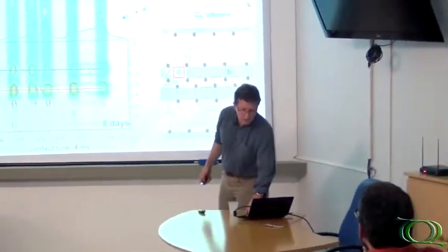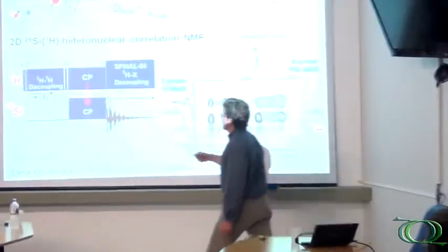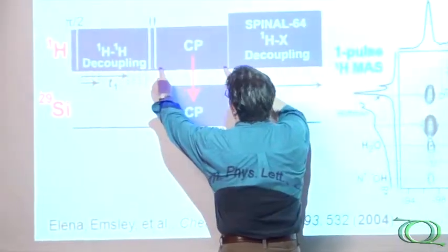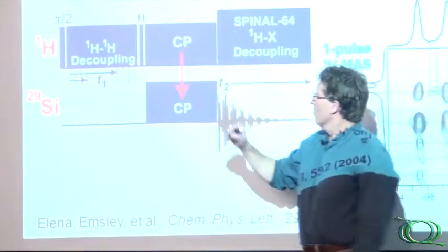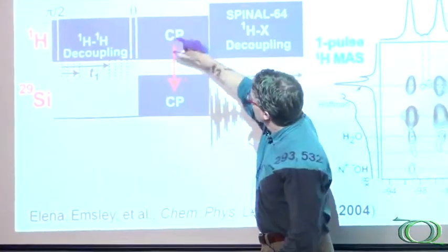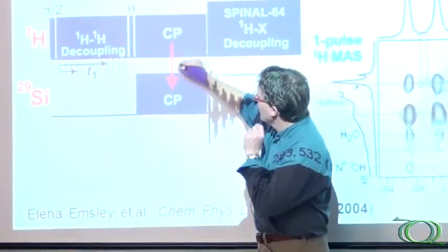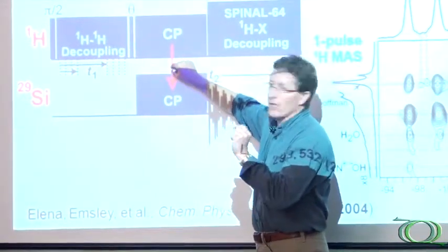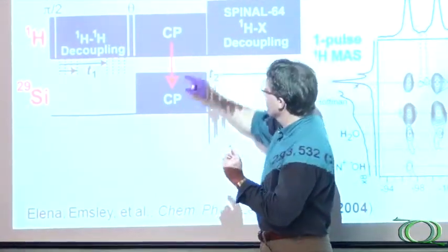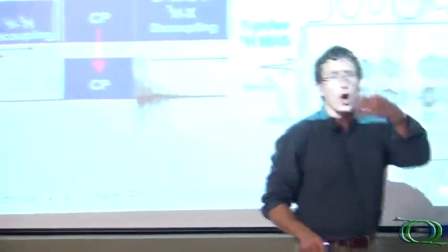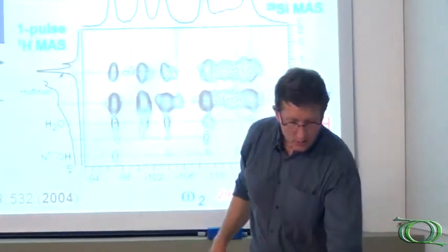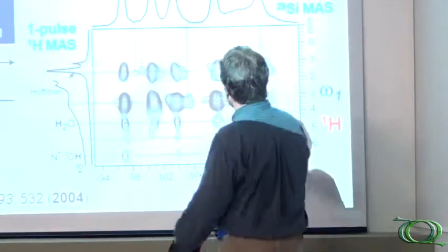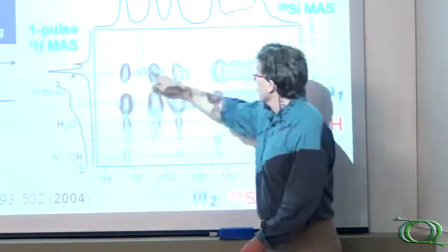So for example, what Tiago was saying is that the contact time at the bottom is 4 milliseconds. That time is only optimized in order to do it. It's the time that you allow this coupling to occur. And this is one of the things that Helmut was also suggesting. The shorter the time, the stronger the couplings that engage. So 4 milliseconds is relatively long.